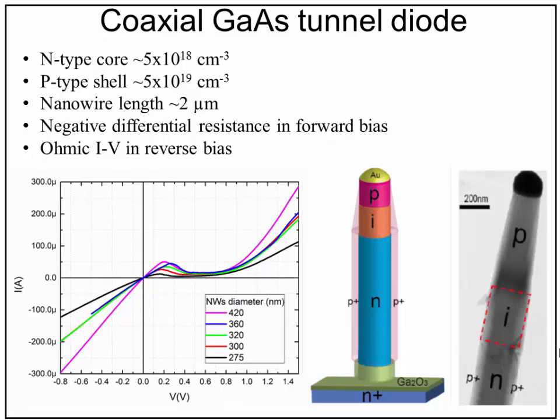After that, having resolved the ohmic contact issue and the outside control on the substrate, here is the structure of the final device. At the very bottom you have the gallium arsenide substrate, it's n+. The substrate is covered with gallium oxide. This basically isolates and protects the substrate from whatever deposition can occur on the surface of the substrate. This oxide is really important.